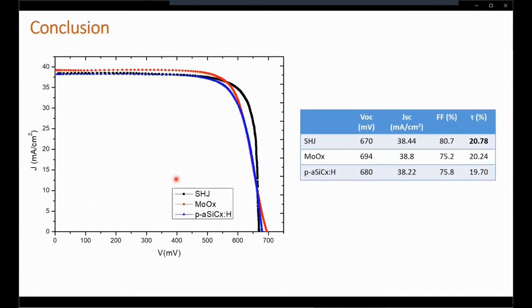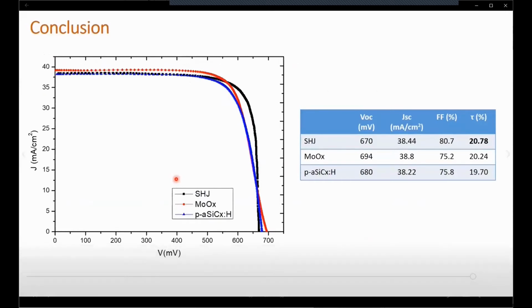In overall results, JSC was improved by 0.5 milliampere per centimeter square. And also specific contact resistivity values are decreased lower than 1 milliohm centimeter square. When we look at the solar cell results, we have achieved record efficiency as 20.8% with standard silicon heterojunction solar cell.